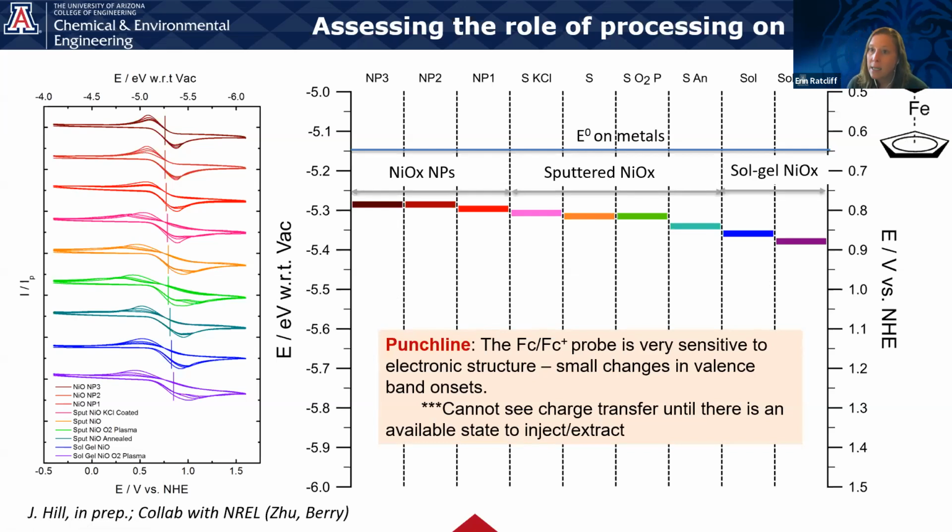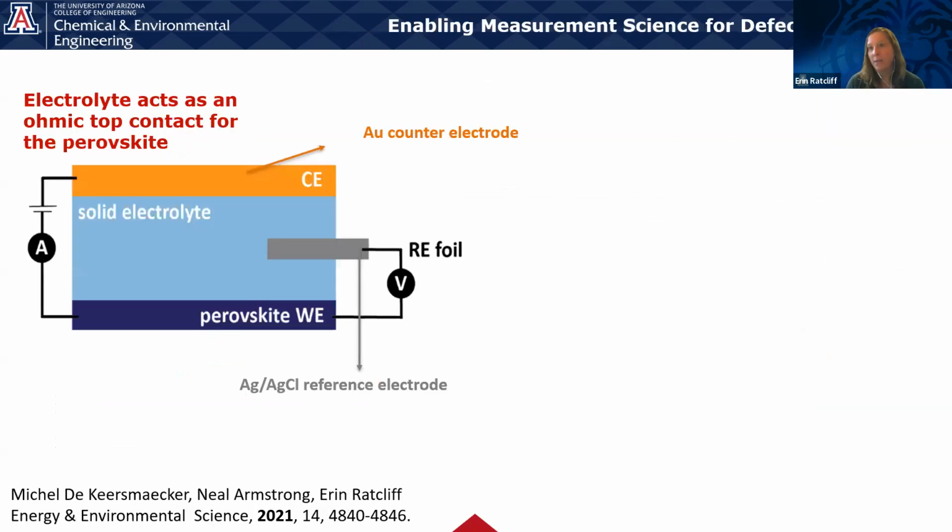Right, so let's take this technique and turn it on to perovskites. And the challenge here with perovskites, of course, is that they're soluble in almost every solvent. It's very difficult to find a non-solvent. And so what we did is we actually just switched to a solid state approach. We use a gel electrolyte. This has about the consistency of a cellophane film, very, very thin. We can include our counter electrode and our reference electrode.